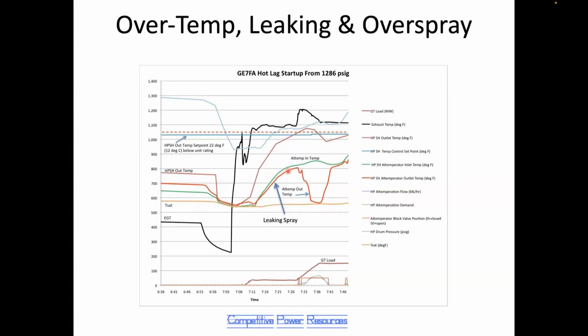The attemperator inlet and outlet thermocouples are in the same steam pipe, 12, 15 meters apart. One's in front of the attemperator spray nozzle, the other is downstream. If there's no water entering the attemperator spray nozzle, those temperatures must be the same. Early in the startup, when steam flow is low, if you see a difference in inlet and outlet, where the outlet is cooler than the inlet, that's an indication that water is leaking by the spray nozzle. This is the point at which the attemperator actually comes into service. The attemperator valves open, and we intentionally cool off the steam at the outlet. Back here, the valves are closed, so this is an indication of leaking water.